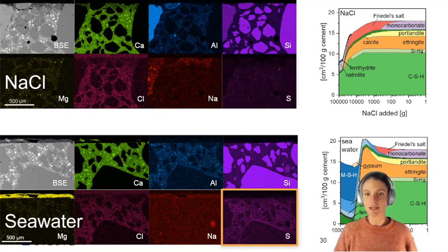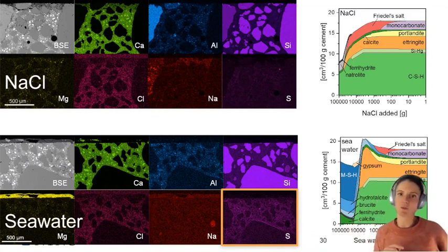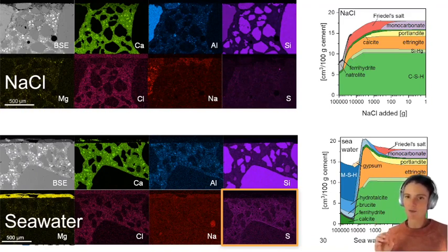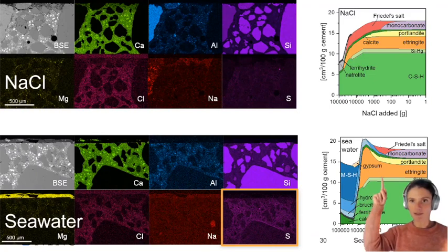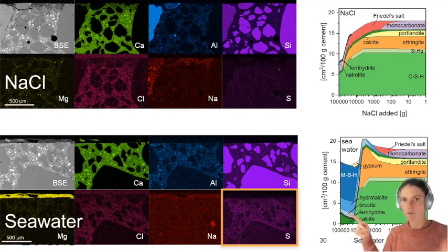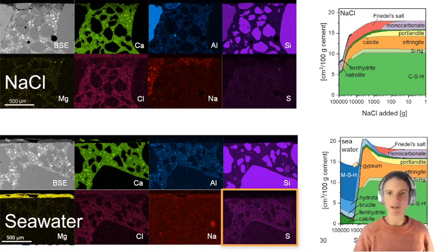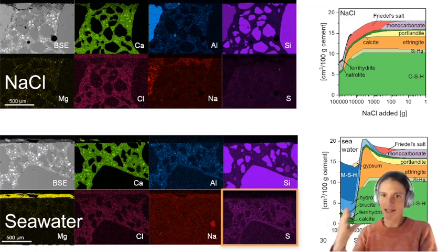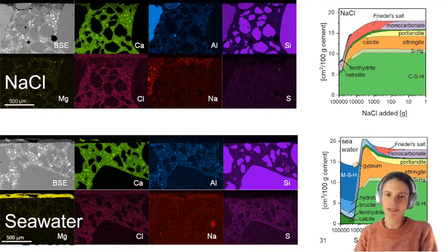And interestingly, when we look at the sulfur, we actually see a sulfur enrichment in the paste. So we do get sulfur from the seawater in our cement paste. And that matches with this model. We do get enhanced ettringite formation towards the surface, more sulfur, and we have the precipitation of this one here, brucite, on our surface. So this very simple thermodynamic model actually predicts kind of what's going on in reality. Now, the question remains, does this magnesium and the sulfur actually affect our chloride ingress? And here's the answer.